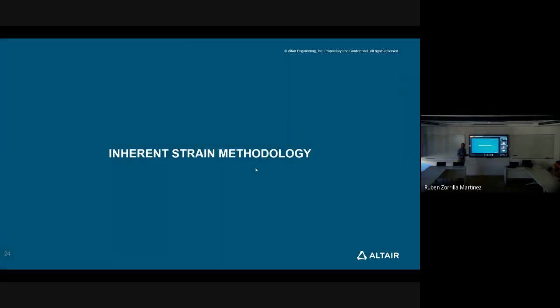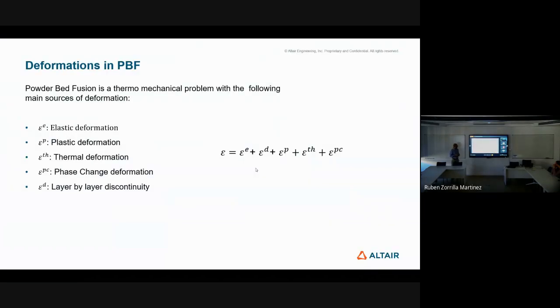So what is the inherent strain methodology? In fact, it's quite simple. It comes from considering the sources of the deformations that we have inside the PBF. First, we have elastic deformation and plastic deformation, the mechanical one. So this is an elastoplastic solution. We have thermal deformation for the shrinkage. We have the phase change deformation, because when you melt and then solidify, there is a big shrinkage on solidification. And we have a discontinuity by layer.